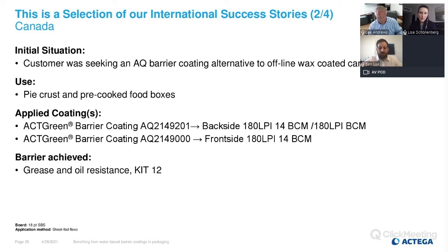In Canada, a customer was seeking a water-based barrier coating as an alternative to offline wax-coated carton stock for the production of food boxes for pie crusts and pre-cooked foods. With our ACTGreen Barrier Coating solutions, we were able to achieve a grease and oil resistance of kit 12 and also provide a recyclable alternative to wax. This was achieved by applying a grease barrier coating on the backside and a balanced system with water and grease barrier properties on the front side. An additional benefit for the customer was a significant commercial saving due to different material and less maintenance and operator time by not using the wax machine.